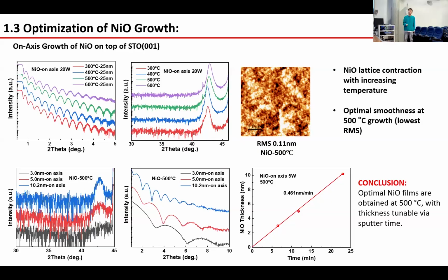So we choose this temperature and then grow other thicknesses like 3, 5, and 10 nanometers, and also obtain the thickness from the reflectivity, and then calculate the thickness dependence on the time, and get the calibrated deposition rate to grow the other thicknesses by tuning the sputtering time.